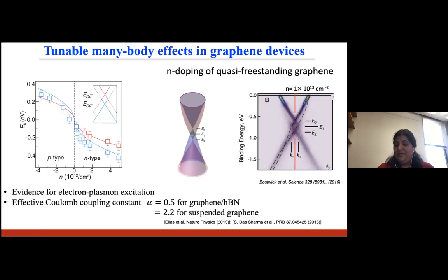But clearly, in their study, they attributed this to plasmaron particles, which are the bound states of charge carriers with plasmons. And so in our study, we see clear evidence for electron-plasmon excitations, and we can convert this separation between these two Dirac crossings into an estimate of the effective Coulomb coupling constant. And if we do that, we find that for our samples, we have a coupling constant of 0.5. And this is the same coupling constant that was observed for this quasi-freestanding graphene.